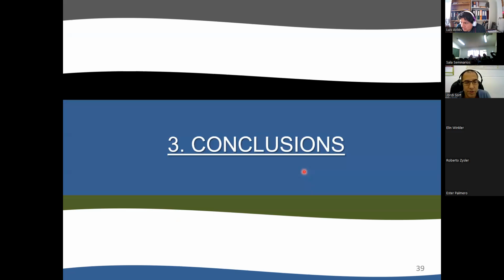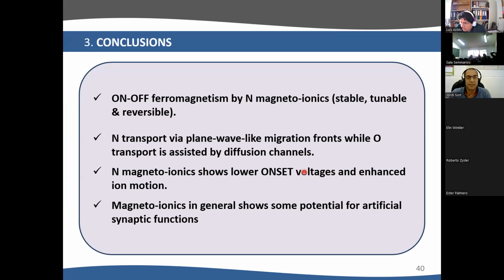Now, in conclusion, what I've shown here is that in some particular systems like cobalt oxide, cobalt nitride, when you apply voltage, you can induce the most drastic change that you can imagine in magnetism, which is to completely suppress magnetic properties or induce them again. This goes beyond the typical observation of people that see a reorientation of the easy axis of the loop, or changing coercivity, or changing magnetization with voltage. So here we completely suppress or generate magnetic properties.